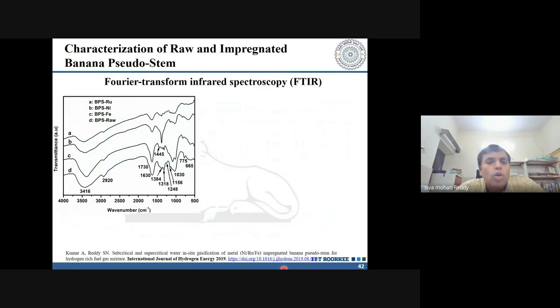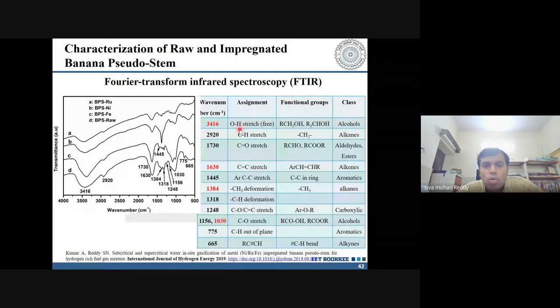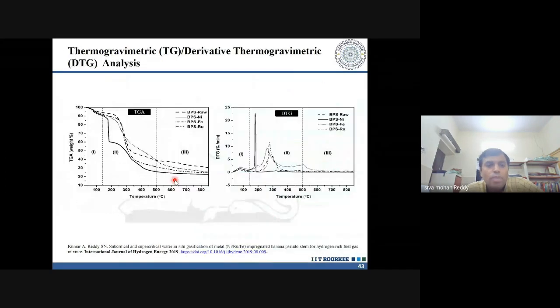Okay, so before we go into more detail about the degradation, one has to understand how these metals are incorporated into your biomass matrix. And you see there is a variety of FTIR peaks. There is an OH stretch, which is present because of alcohols. This stretch happens because of the attachment or interaction of your metals with the alcoholic group component, that is the cellulosic components. You have a 1630, which is a C=C stretch related to the alkenes, and one related to the alcohols, that is 1156, and you have 1033, which corresponds to the alcohol as well. You see this is very much reduced, which indicates that there is an interaction between the metals and the functional groups present on your biomass matrix.